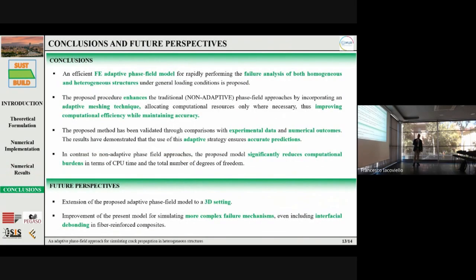So, in conclusion, an efficient finite element adaptive phase field model for reproducing crack propagation phenomena in both homogeneous and heterogeneous structures is proposed, which enhances the traditional phase field approach by incorporating an adaptive mesh technique, allocating computational resources only where necessary, thus improving computational efficiency while maintaining accuracy. The proposed method has been validated through comparison with experimental data and numerical results, thus denoting that this strategy ensures accurate prediction. In addition, compared with the non-adaptive phase field approach, the proposed model significantly reduces computational burden in terms of computational time and the total number of degrees of freedom.